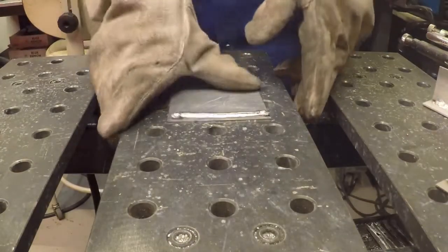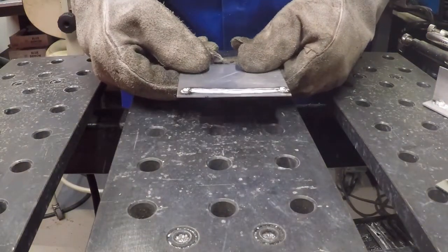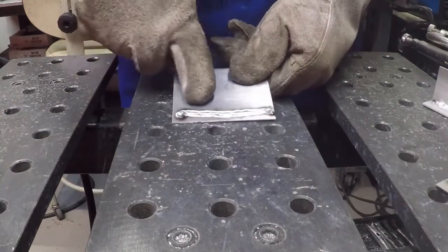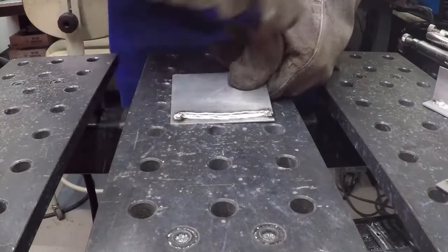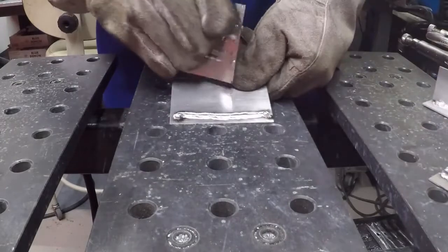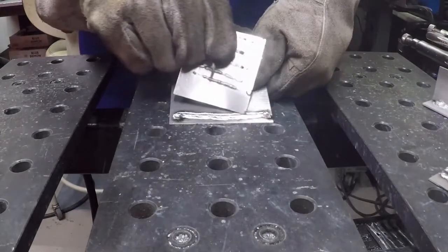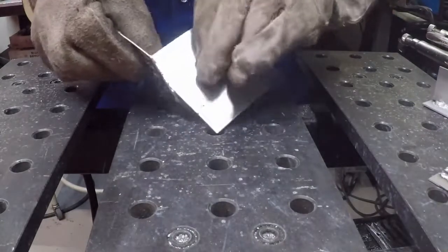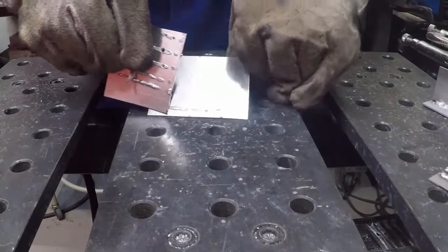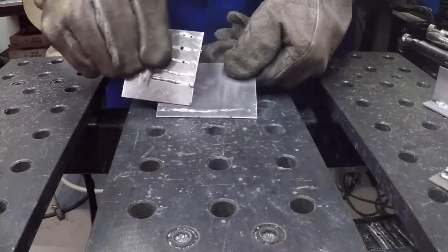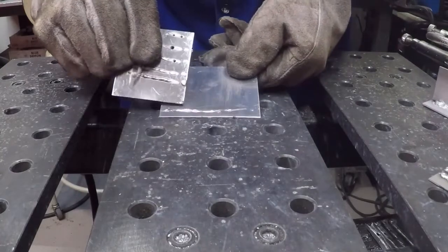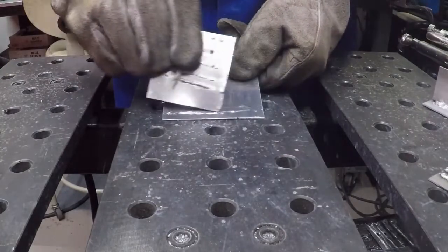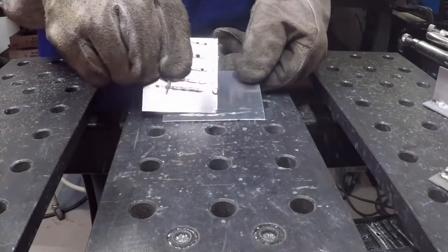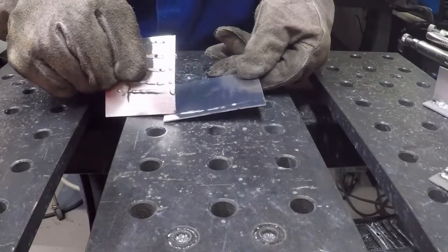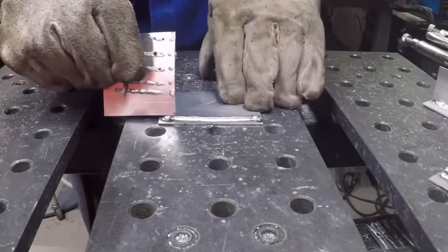All right, let's take a look at that weld. I went much faster here than I did on steel. So my weld looks okay. It's relatively consistent. You can see as I get down to this end, I've slowed down just a little bit because my weld is getting flatter. And you can see even at that speed, because I'm not consistent, down here where I'm flat, I'm getting much more penetration. Up here where I'm a little faster, I'm not getting as much penetration, but all in all, not too bad. Let's try it again and see if I can get a little more consistent.